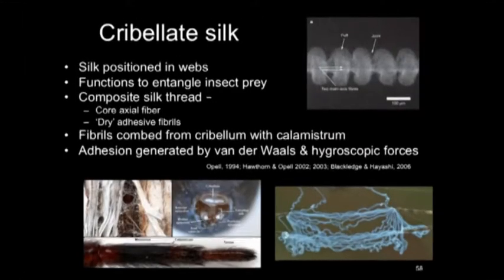These are silks that are similarly used in webs, and webs of all kinds, whether they're sheet webs or webs held by spiders in their arms. And they similarly function to entangle insect prey, much like those gluey threads, but they're composed of a different type of adhesive. They act on these dry adhesive fibrils, as I talked about a little bit before, that form these sort of puffs. And while it's difficult to see, these are actually hundreds to thousands of little nanofibrils that act like a glue, and they're supported primarily by these core fibers. So they operate as a composite with two different materials that operate as one.